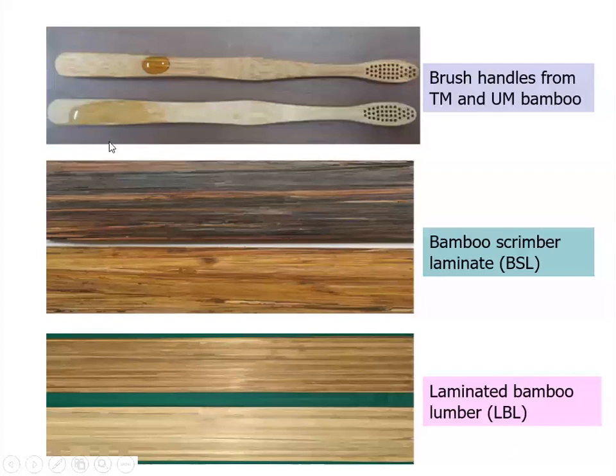This is the process here. You take the bamboo, and the outer green layer is generally removed. We are also trying to retain the green layer and flatten it, but at this point of time, we are removing the outer green layer, and then a small cut is made on the bamboo. Either one small cut, or it can be split into two, and then it needs to be softened in steam. Once it is softened, it can be placed under the roller to flatten it. And then this is the flattened bamboo. It looks like this. This is the flattened bamboo which we have produced here.